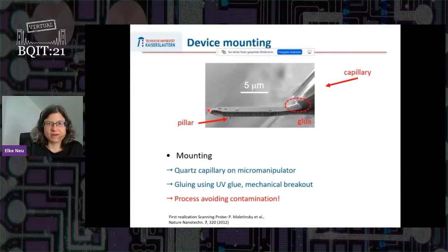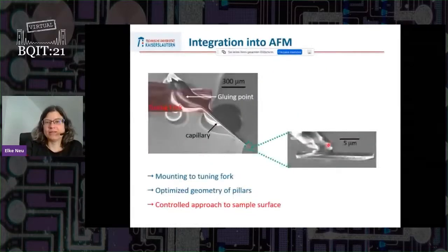This you can see here. Here it was connected to the rest of the sample, and this connection has been broken. It has been broken by gluing the device to a quartz capillary and then just pushing, and you break it off of the rest of the devices. And here's the pillar facing down towards the sample. This really works with micromanipulation, bringing the capillary in contact, gluing it, and then you have one device here that you can mount to a tuning fork based AFM, and you can do the scanning NV measurements with it. So this is the principle of all these experiments.